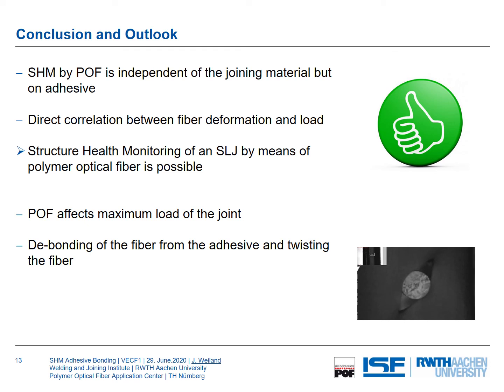I want to come to my conclusion. I showed you in general an overview about SHM and adhesive bonding. Our method is an intrinsic method, so independent of the adherent but dependent on the adhesive. We saw the direct correlation between the fiber deformation and the stress of the adhesive joint. So we think we are on a good way to develop a new method for structural health monitoring of single lap joints. There are two things we have to focus on. The big thing is the debonding of the fiber to the adhesive, and therefore we also do not yet reach the maximum load of the joint.